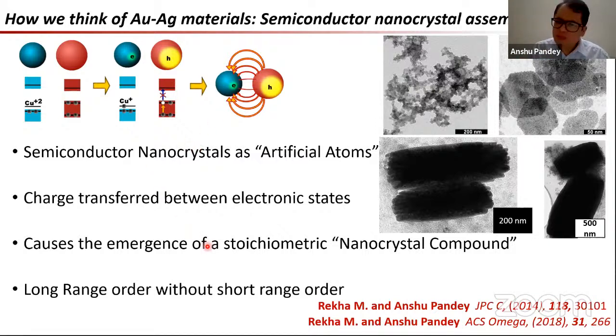So there are many, many interesting things which happen all at once. But what is most interesting and noteworthy in all of these materials is that even though some of these assemblies, say these nanorods or these drums, would consist of millions of nanocrystals pulled together by this Coulomb force, it appears that they seem to have some form of an order. More precisely, they have a long-range morphological order, while completely lacking a short-range order. This is a rather weird thing.